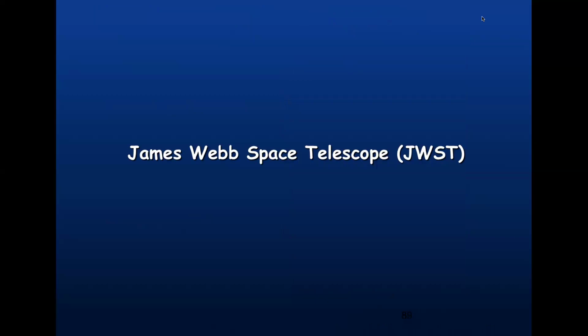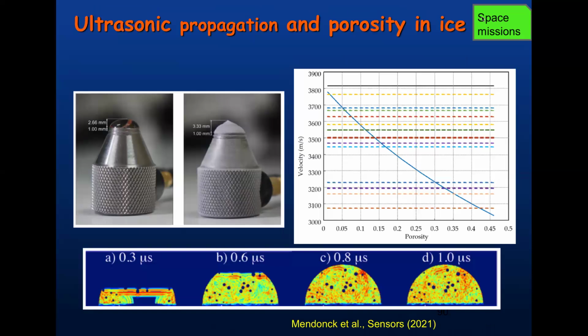We are also working with James Webb data. So in particular, and this is something for Olga and Fernando, we are also interested in porosity. So we came in contact with physicists at ITEFI CSIC, to use ultrasound to measure porosity, which is totally crazy. But we got an Explorer project to do this, and we could just play with it. And we started using this transducer, which is emitting an ultrasonic pulse. We just put a water drop on it, and we freeze the drop. So we measure the transmittance of ultrasound through liquid water and also through water ice. And we measure different velocities of propagation of the signal.